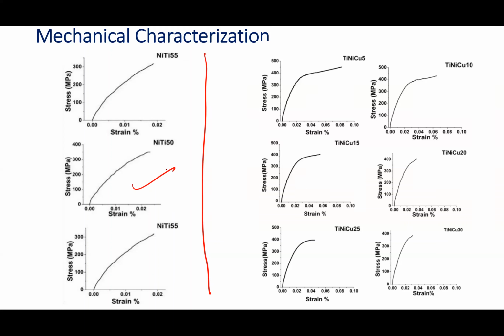In the case of the ternary alloy, it is clear that the elasticity of all the samples has reasonably improved compared to the binary alloy. There is a uniform and smooth growth of the curve initially for all the samples, gradually for NiTi Cu5 and NiTi Cu10. Then after reaching the yield strength level, the formation of a plateau is seen, which is quite similar. The presence of this martensite orientation drives the transition curve to a plateau formation in the sample.